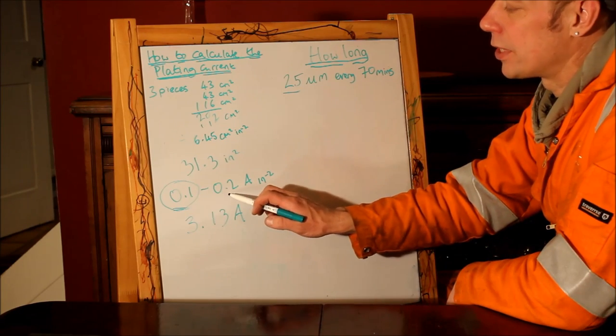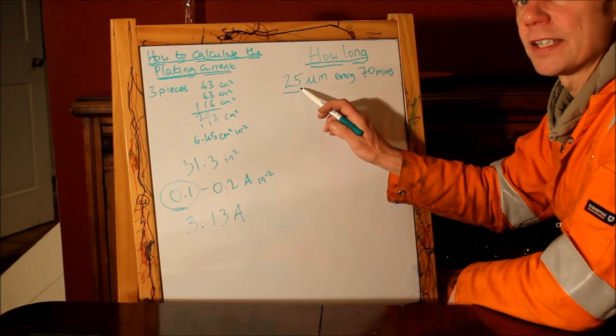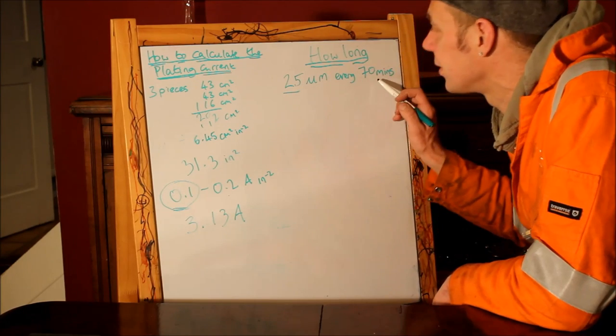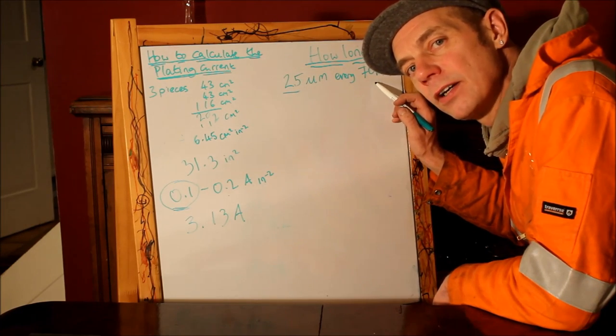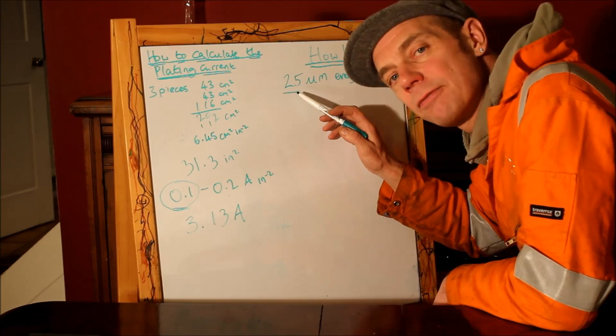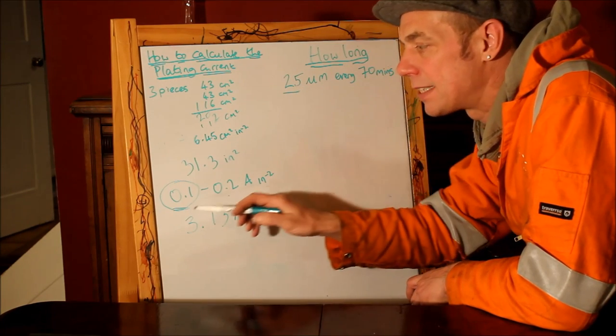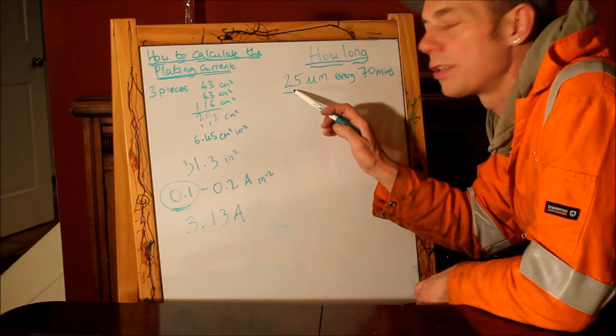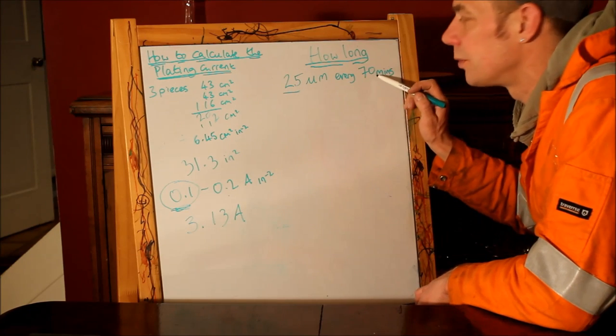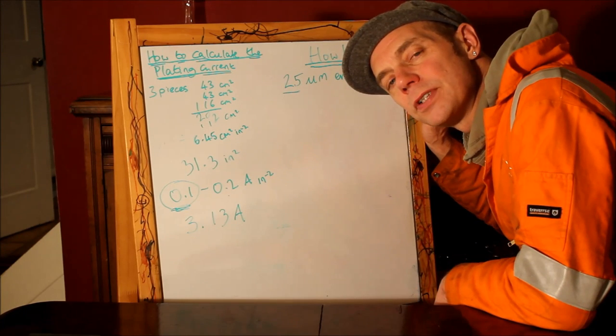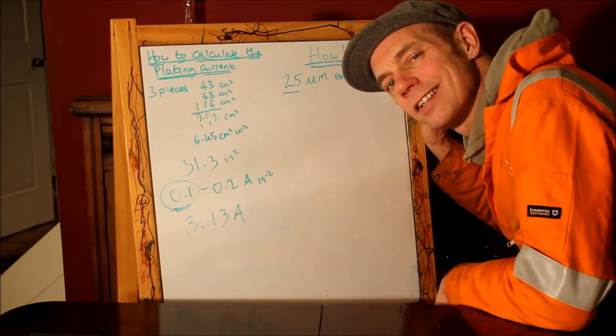If you plate at 0.2 amps per square inch, you'll halve that time. So you'll deposit 25 microns in about 35 minutes. All right? If you want a thicker deposit than that for whatever reason, so if you're plating at 0.1 amps per square inch and you wanted 50 microns of thickness, you'll just need to double that time to 140 minutes. Got it? All right.